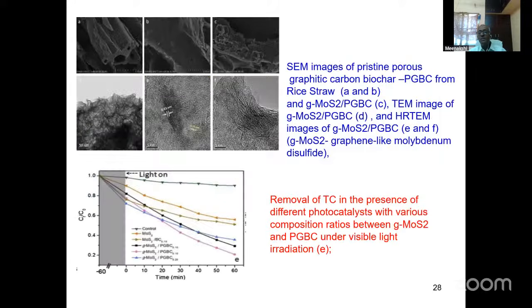And this is another one, porous graphitic carbon biochar. This is prepared from rice straw. You can see the morphology, and A and B are images of this biochar. And this is molybdenum sulfide, that is graphene-like molybdenum sulfide. Just like graphitic carbon nitride we say g-C3N4, here we call it GMoS2, graphene-like molybdenum sulfide biochar. You can see the TEM images, and again these fringes are characteristic of molybdenum sulfide.